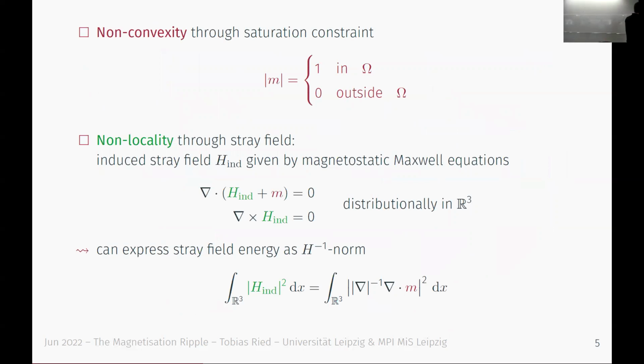Now, notice that the variational problem, since we're really interested in what happens once everything has settled down in the saturation magnetization, we can always normalize it, and I will set it to modulus 1 in my material and continue it with 0 outside. But that produces a non-convexity in the variational problem. And since we have this stray field energy, and the field is given by a solution of Maxwell's equations in the static situation, we have a non-locality appearing.